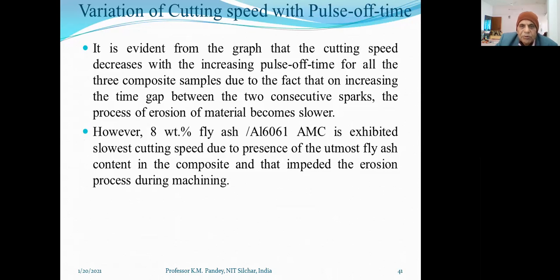Then it is evident from the graph that the cutting speed decreases with the increasing pulse off time for all the three composite samples, due to the fact that on increasing the time gap between two consecutive sparks, the process of erosion of material becomes slower. However, the 8% weight fly ash A6061 composite exhibited the slowest cutting speed due to the presence of the utmost fly ash content.